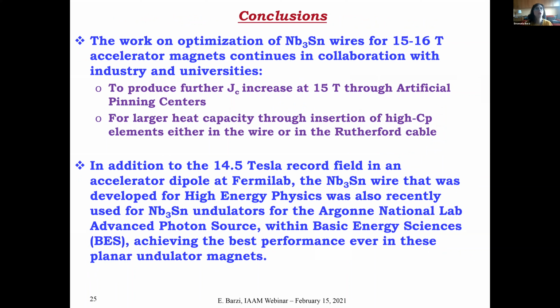So in conclusion, the work on optimization of these niobium-tin wires for our very high field accelerator magnets for high energy physics actually continues in collaboration with industry and university. It's very much a global research. Japan is involved, Europe, CERN are involved, and of course the US are involved, because we still want to improve Jc, the critical current density in these materials, and now the research going on through artificial pinning centers looks very promising and has already shown that it works on very short samples. So now we have to scale up to longer wires. And also we need to improve the heat capacity, the specific heat of these superconductors, because this would very much improve their stability under temperature fluctuations in these magnets.